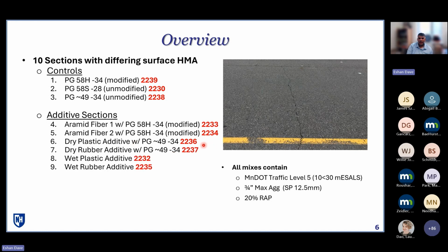And then lastly, you have cells 32 and 35. And these are wet additives, which are typically reacted into the binder at the terminal rather than directly added into the mix, as in case with the dry additives.